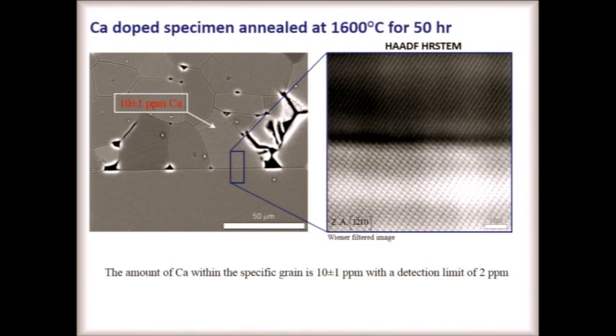So I said that the calcium is going to the grain boundaries and it's doing something exciting, but I didn't prove it to you that it's actually there. So here's an experiment where we did the diffusion bonding. This is the basal plane sapphire growing into the polycrystalline alumina. This particular grain was really big. We went in and did WDS and only measured 10 ppm, so it's a little bit less than the mean,